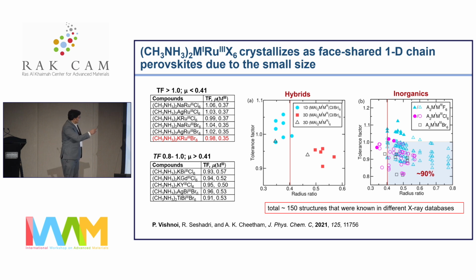So all these 3D perovskites, when we plot them in this map of radius ratio versus tolerance factor, occupy this corner, which is high radius ratio and low tolerance factor. Whereas the 1D perovskites occupy the corner here, which is high tolerance factor and low radius ratio. So with all the known structures, we thought this could be the reason why our compounds are forming one-dimensional structure. And then we looked to see whether this model, which we designed here, works for